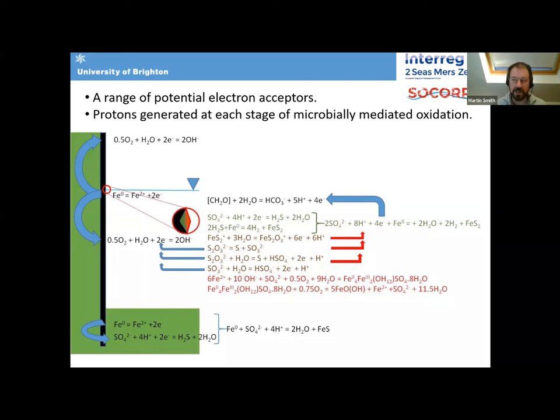So sorry, this is a horrendous diagram, huge number of equations on it, but essentially we have at the steel surface, sulfate reduction, generating hydrogen sulfide that's reacting to produce pyrite. We've then got sulfur oxidizing bacteria and probably iron oxidizing bacteria that are converting that sulfide into thiosulfate and sulfite and ultimately back into sulfate. And at every stage of that microbially mediated metabolic pathway, we're generating acidity. We've got a little sulfuric acid factory forming on the steel surface. So this is what's responsible for the rapid marine corrosion rates.